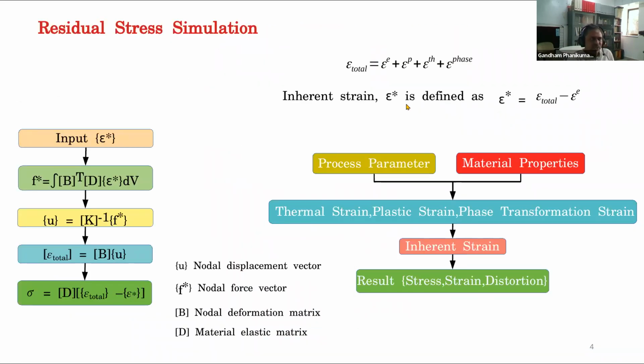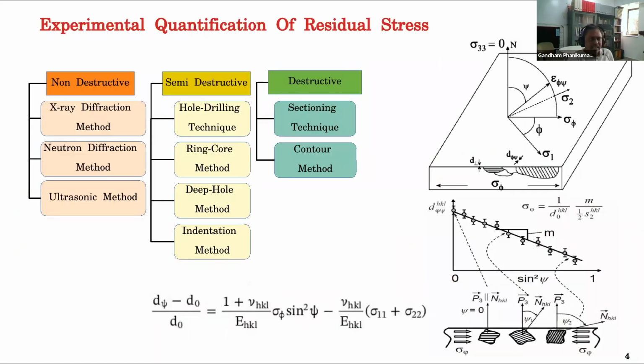And they can take into account the thermal stresses, thermal strains, and phase transformation strains, and so on. So elastic, plastic, thermal, and phase transformation, all the strains can be taken into account. And we can then go on to quantify the residual stress in any component using the X-ray diffraction technique. And we can also do other techniques like hole drilling or whatever. But the X-ray diffraction technique is the most commonly used.